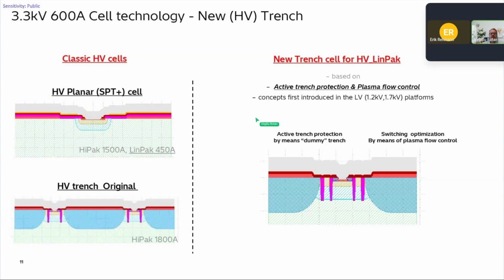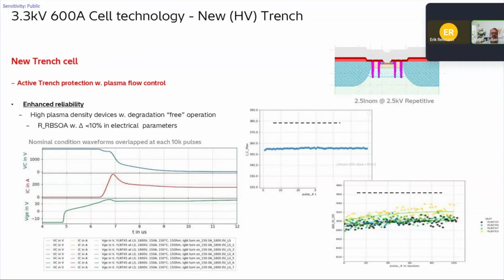And this new trench that we now develop for this device has some active trench protection. So we know the trenches have, from a functioning point of view, when you switch off, the danger of affecting the bottom of the trench, the oxide at the bottom of the trench, with hot carriers. So we do dummy trenches to protect that. We have active plasma flow control, and to demonstrate and make sure that we have a stable trench,